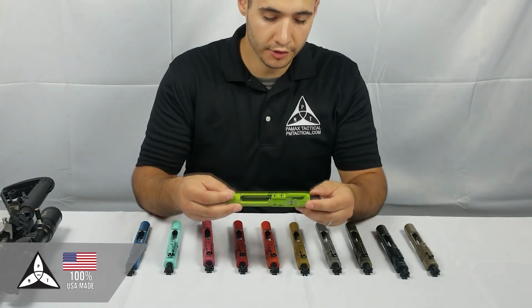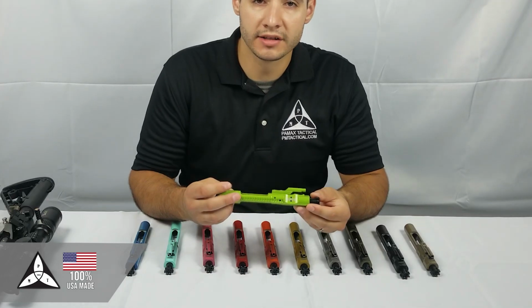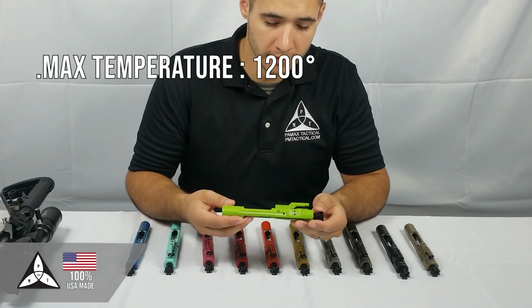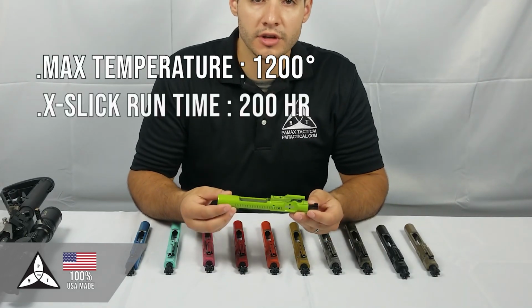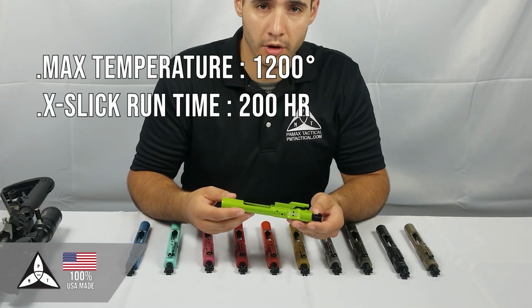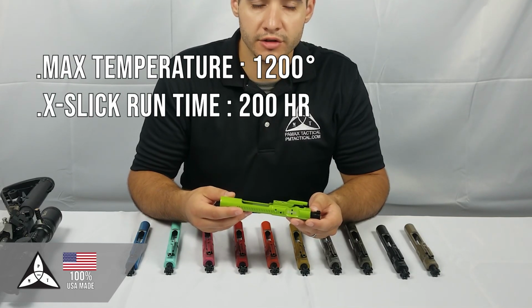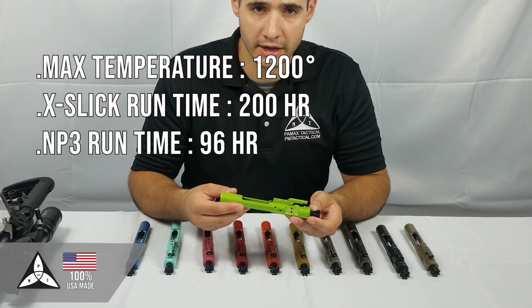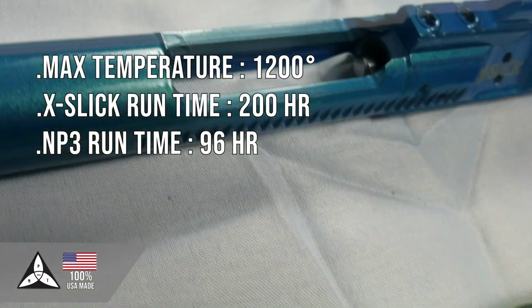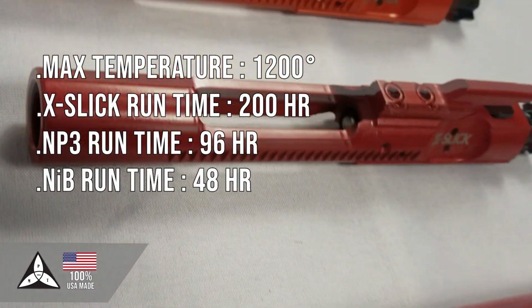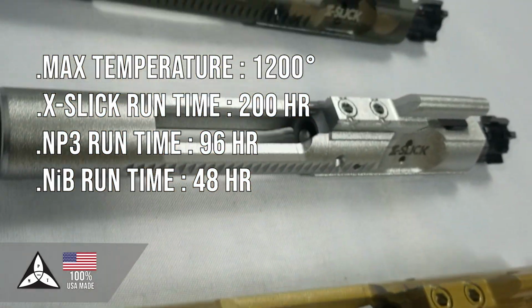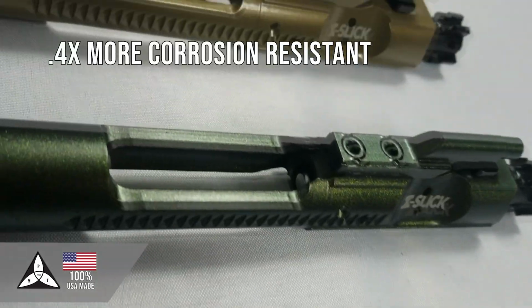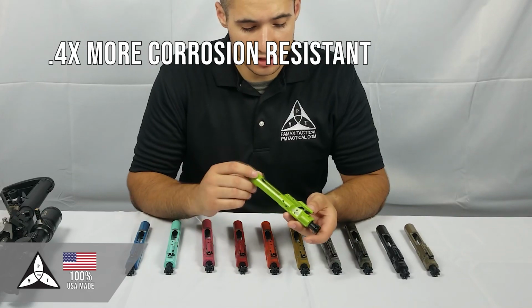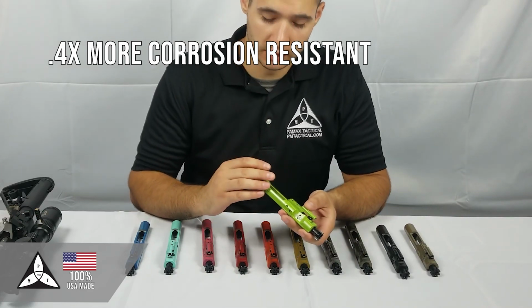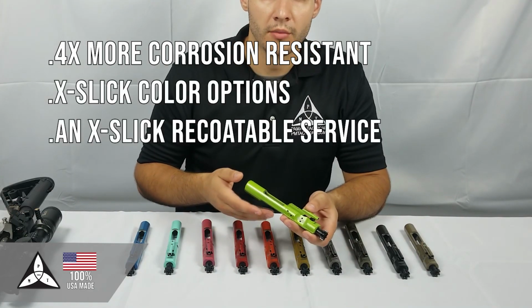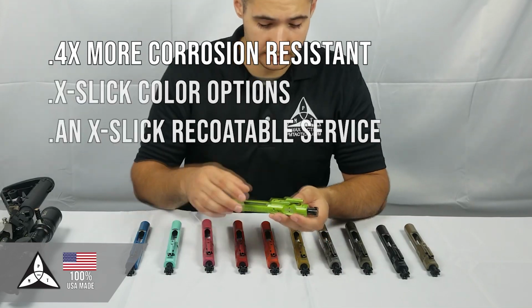XSlick coating is also rated for a max temperature of 1200 degrees and features a 200-hour runtime on our corrosion test, compared to nickel Teflon, which was 96 hours, and nickel boron, which was 48 hours. So this coating is 4 times more corrosion resistant than nickel boron bolt carrier groups. And it offers the key feature not only of a color option, but also a recoatable service.